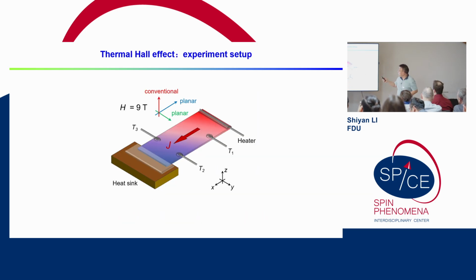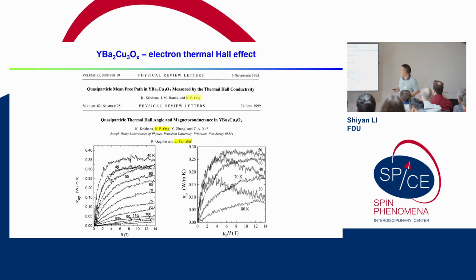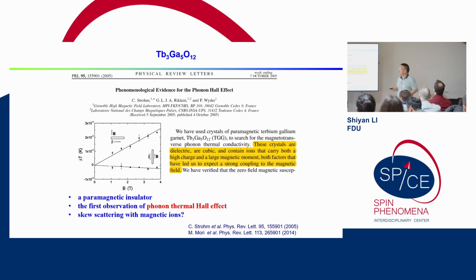This is our experiment setup, and the previous speaker has already explained it. In early days, Professor Ong and Louis Taillefer measured the thermal Hall conductivity for cuprates. That's for electrons. The first experiment on the thermal Hall effect in an insulator was in 2005. This French group checked the transverse thermal signal for this compound. It's a paramagnetic insulator, and they observed a transverse signal of the phonon thermal Hall, because it's paramagnetic, so this should be the phonon thermal Hall effect.